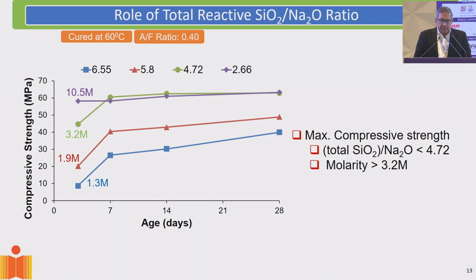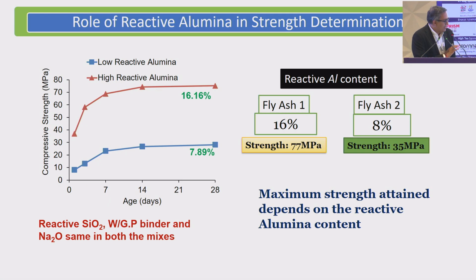And the optimum ratio of reactive silica to sodium in the system is anywhere between 4.72 and 2.66. So that is basically the optimal ratio that will give you the best-case strength from the system, where you use up all the reactive material in the fly ash.